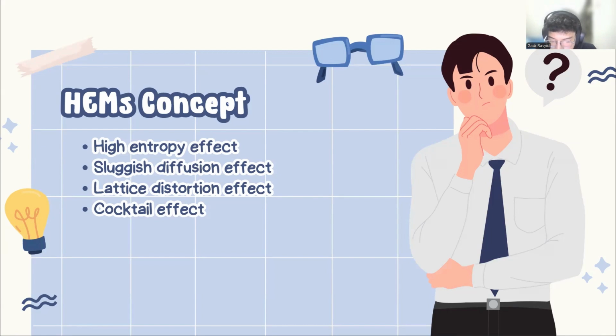When the delta G mix is negative, high temperature favors the stable single phase structure formation, while when the delta G mix values are positive, they favor phase separation. However, in a high entropy system, delta S mix offsets the influence of delta H mix. The delta S mix consists of four parts. The first one is configurational entropy, then vibrational entropy, electronic random entropy, and magnetic dipole entropy. But many studies suggest the delta S mix is dominated by delta S conf.